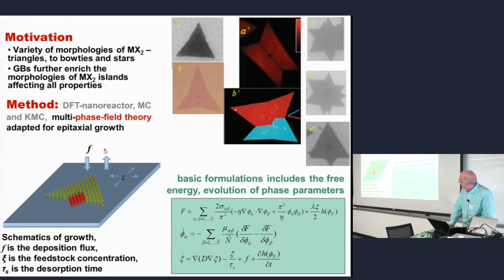We do a lot of work on growth. And the problem with all the class of TMDs is that there is almost nothing known about the CVD mechanism. Actually, people don't do CVD. Mostly they do this kind of cooking, baking mechanism because they don't have gas composition. Good CVD means that you know what your gas precursor is. In most experiments synthesizing this stuff, they just start from solid oxide, heat it up, and something happens, and what is in the middle so far remains unknown.